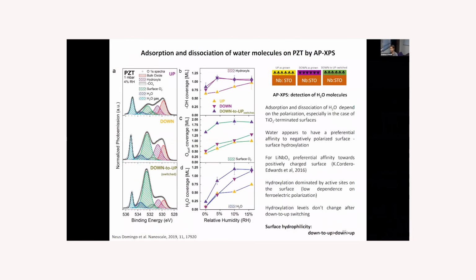So, in our experiments, we have studied different PZT samples by ambient pressure XPS. This is lead zirconate titanate, which was grown at the University of Geneva in Patricia's Paruch group. We had the as-grown up surface, the as-grown down surface, and then the down to up switched surface. So by comparing these surfaces, we could see that in the oxygen peak, we have many contributions.